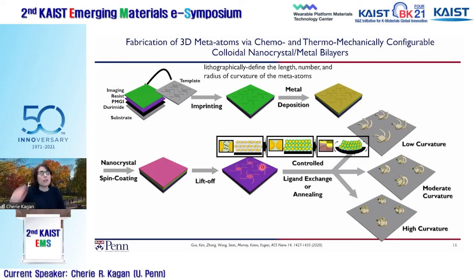And so we were interested to see that we could fabricate large area templates. We could use this process of imprint lithography, and then we could deposit metal on the bottom. We could deposit nanocrystals, make these bilayer structures, and then we could exchange their surface and get them to fold in three dimensions. And what we learned a little bit more is that we could further control that even by thermal annealing, and get them to fold even more. And so it gave us a way, by using one simple patterning step, to create these three-dimensional surfaces to make chiral metamaterials.